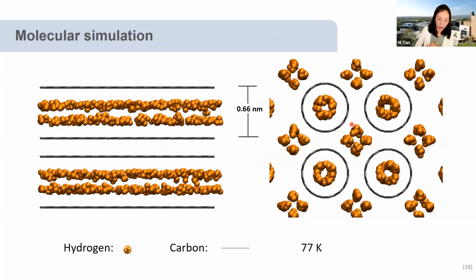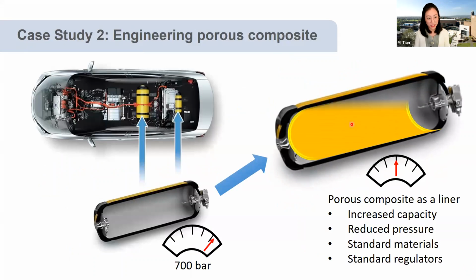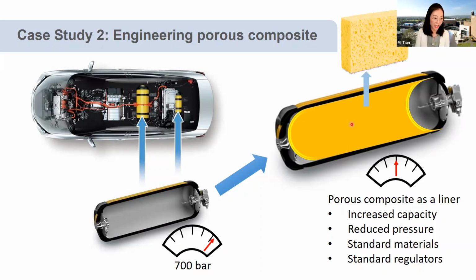So now we know from this theoretical study that we identified the optimal pore size, less than 1 nanometer, ideally 0.7 nanometer, and the pore shape. Based on this investigation, we want to develop a porous composite as a liner to line the hydrogen storage tank, in order to either increase the tank's capacity or reduce its pressure. Therefore, we can use more standard materials and standard regulators so that the tank's cost will be reduced greatly.